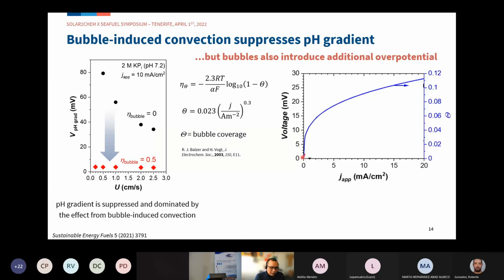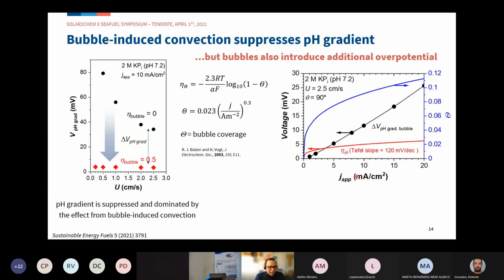We plotted here the bubble coverage from this simple equation as a function of the applied current density, and then we can compare the overpotential, which is the negative effect of bubbles, versus the positive effect of bubbles, which is the suppression of the pH gradient as mentioned here.